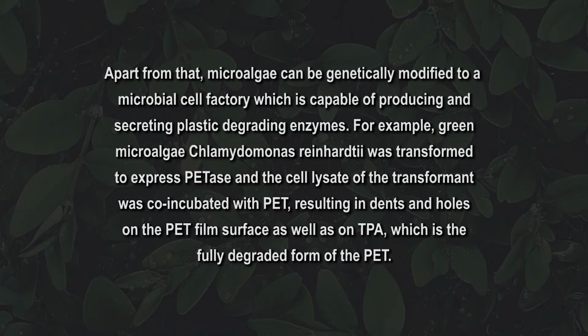Apart from that, microalgae can be genetically modified to a microbial cell factory, which is capable of producing and secreting plastic degrading enzymes. For example, green microalgae Chlamydomonas reinhardtii was transformed to express PETase, and the cell lysate of the transformant was co-incubated with PET, resulting in dents and holes on the PET film surface as well as on TPA, which is the fully degraded form of the PET.